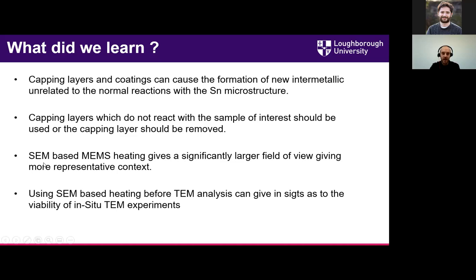We really found that SEM-based heating gave us a significantly larger field of view, which gives us a much more representative area to look at, and also made sure you could see large-scale effects like those tin nodule growths that you wouldn't necessarily see before doing TEM. So our best practice in the center really now is to do SEM-based heating before TEM-based heating, if possible, as it allows you to iron out any of these sort of issues that you might come across but wouldn't see in the TEM.